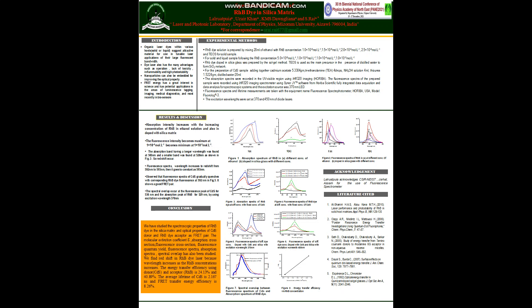And for the preparation of cadmium sulfide, we add together cadmium acetate, triethanolamine, NH4OH, thiourea, and distilled water. The spectra, that is absorption and fluorescence, were recorded in UV-visible region using Horiba imaging spectrometer and SynerJY software.